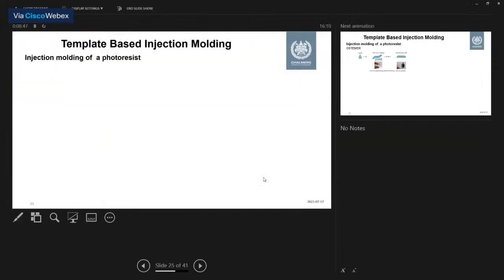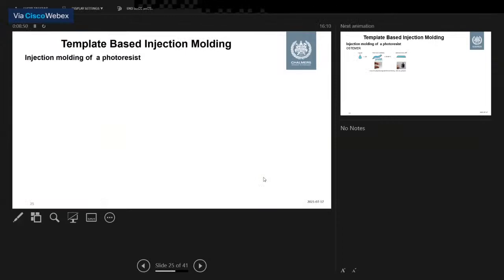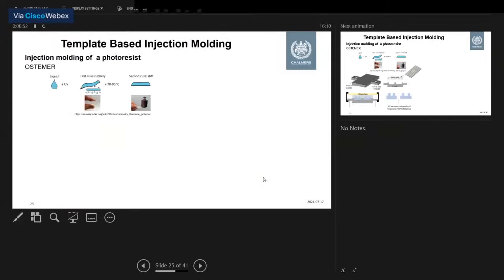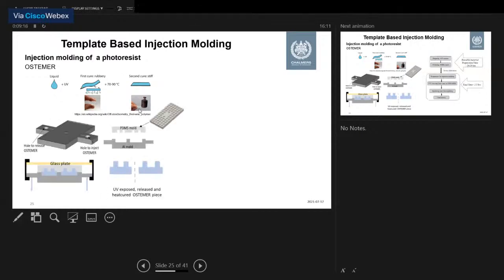And then we design an injection molding process. For injection molding, we use a newly developed photoresist, which is OSTEMER. The benefit of using OSTEMER is you can use it at room temperature, and after UV cure, it becomes a stiff or rubbery structure, and that can be easily released or removed from the substrate. And then when you heat cure it, it will get the final stiffness. So this is how we plan the injection molding process.